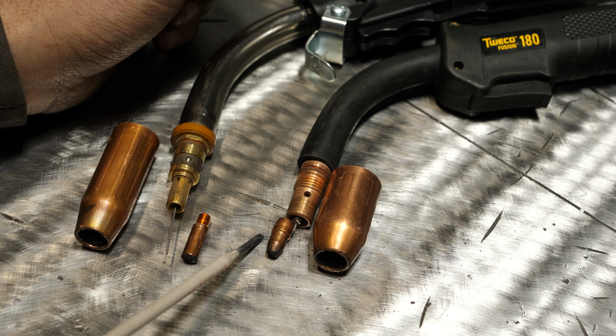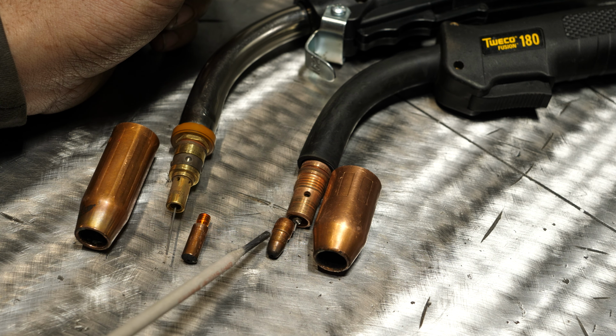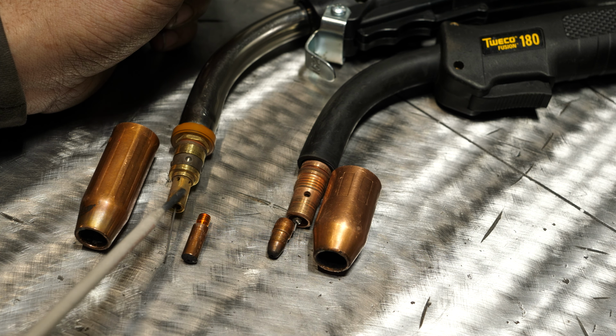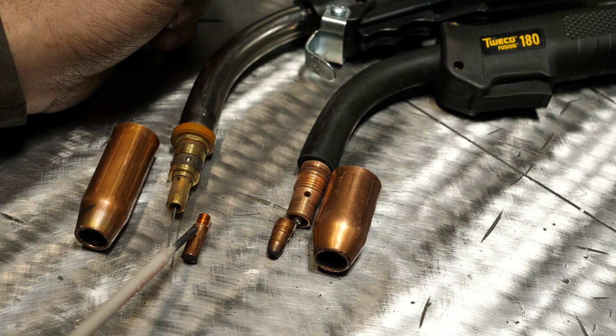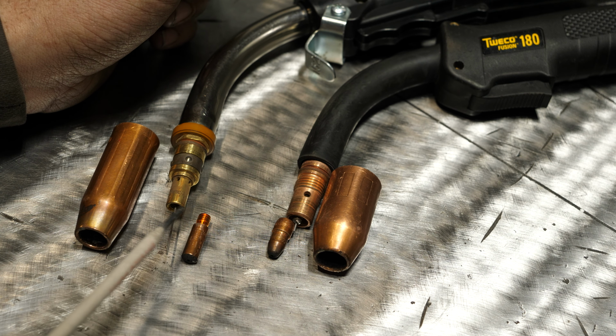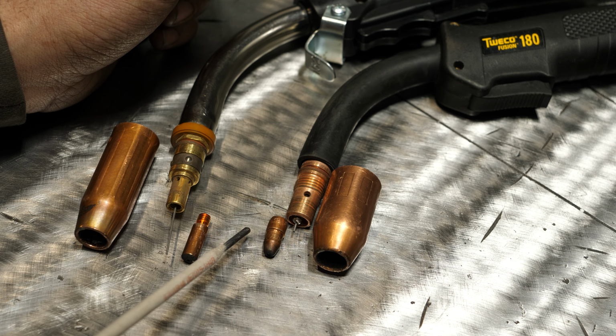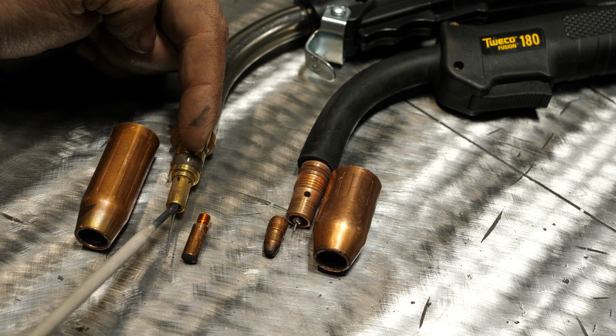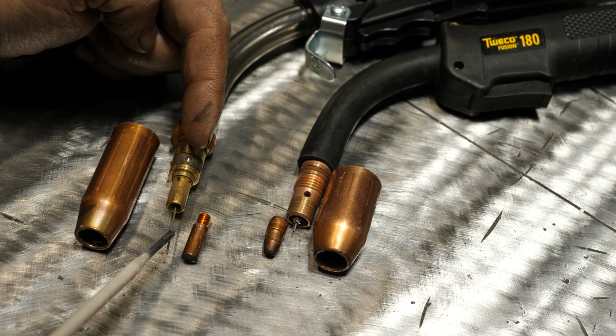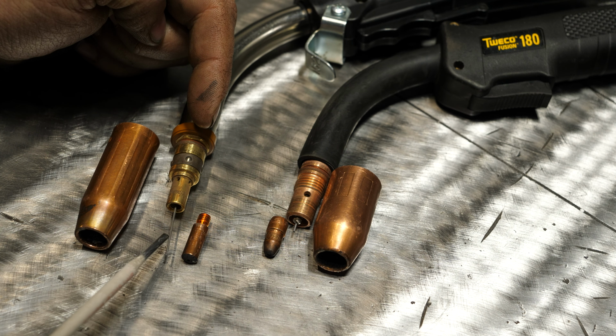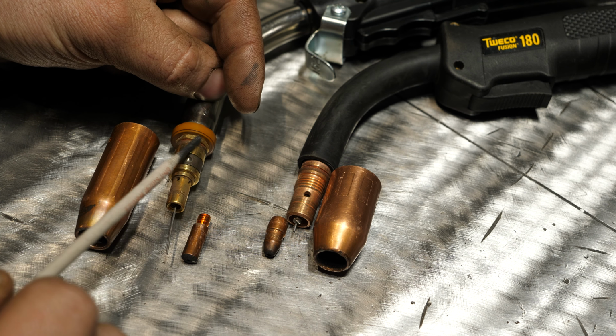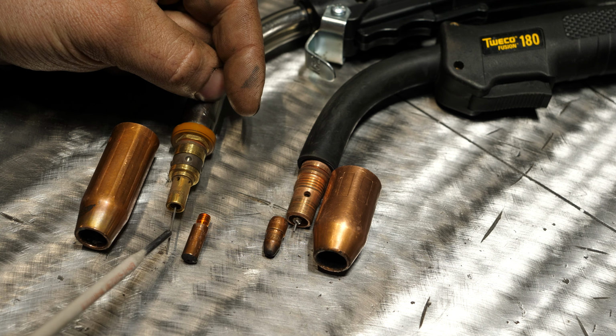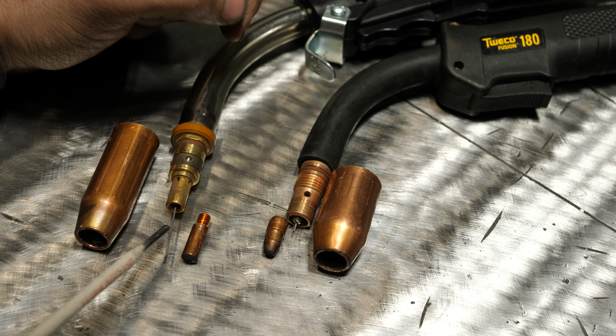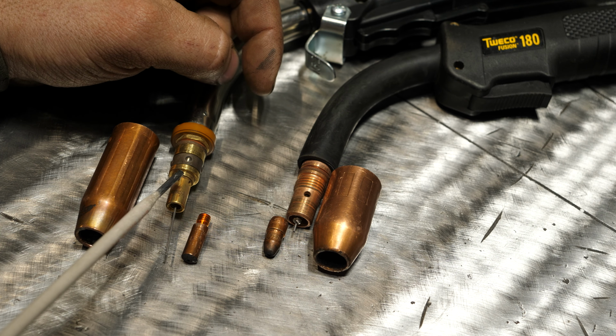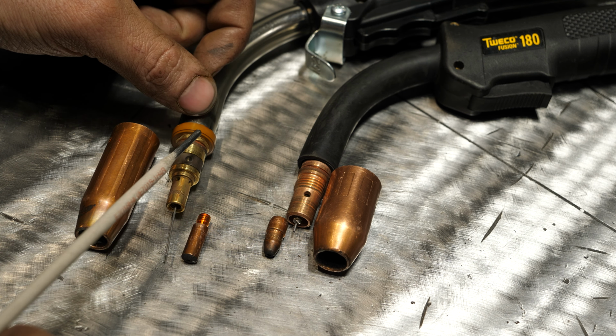Now, the one here, the Tweco 180, uses contact tips that are held in by the nozzle. This Spraymaster uses screw-in contact tips. I much prefer the screw-in type. You know it's tight, because you don't want to have a loose connection in that, but this does work pretty good. The main difference here is a contact tip being so much longer puts all the heat far, far away from the gun itself, which is hugely important because when you're running 200, 250 amps at 26 plus volts, you're gonna run into a lot of heat, and that heat has to go somewhere.